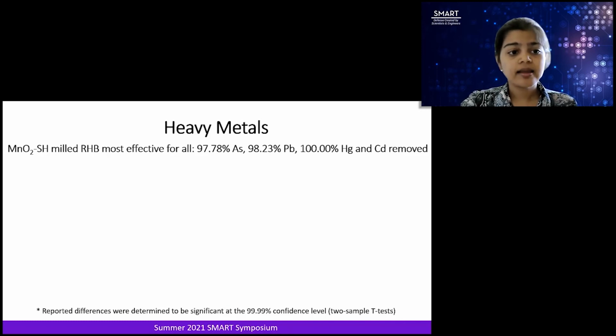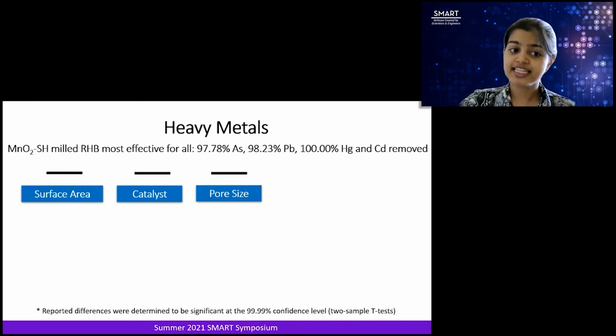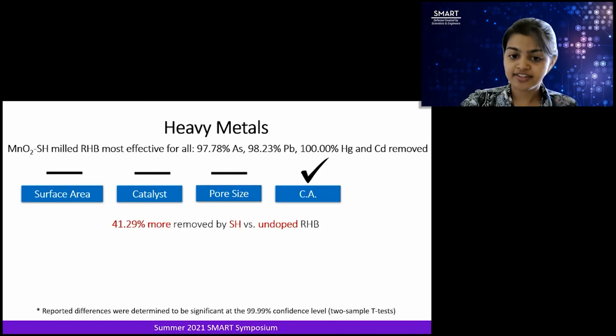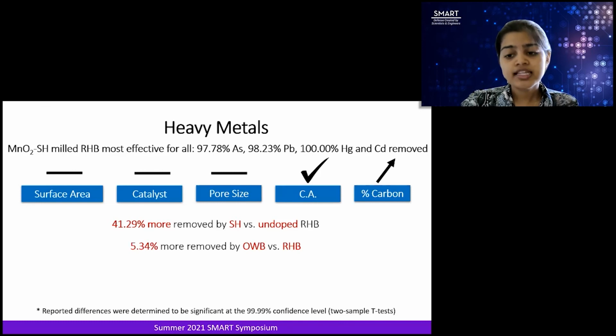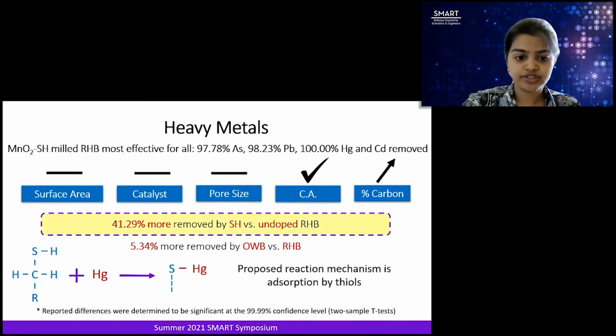Now let's look at heavy metals. Manganese oxide thiol-doped milled rice husk biochar was by far the most effective, removing 97.78% of arsenic, 98.23% of lead, and 100% of mercury and cadmium. However, there was no statistical difference in the data between surface area, catalyst presence, and pore size. However, there was a significant difference between thiol-doped rice husk biochar versus undoped rice husk biochar. Thiol-doped biochar removed 41.29% more heavy metals on average. This tells us that complexing agent presence is key for heavy metal sequestration. Similarly, increased carbon composition resulted in 5.34% more heavy metals removed.